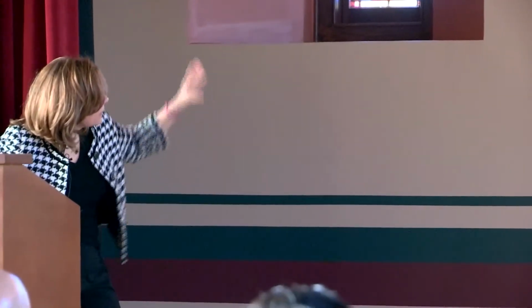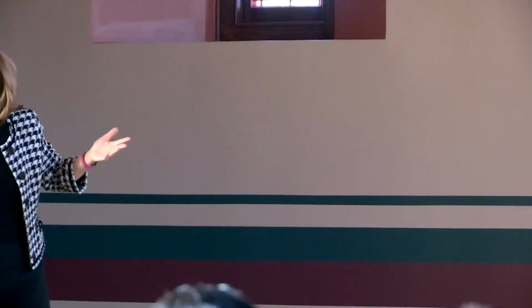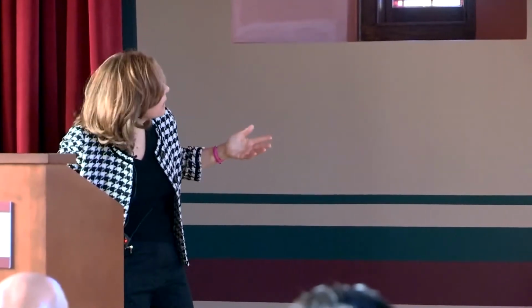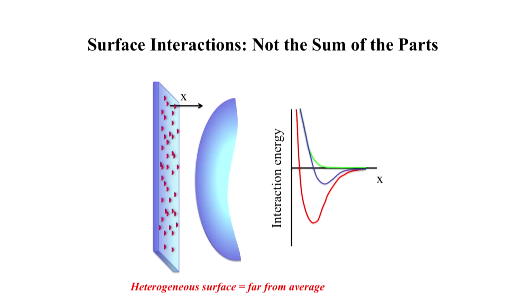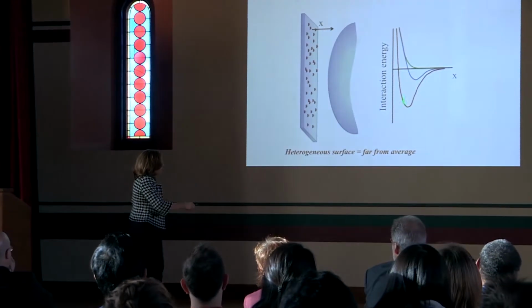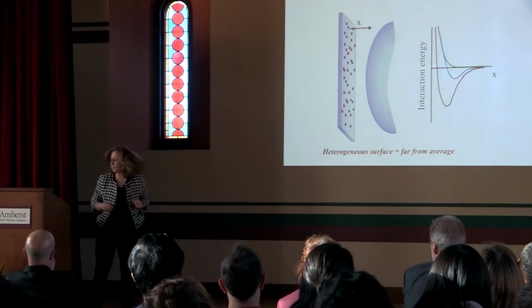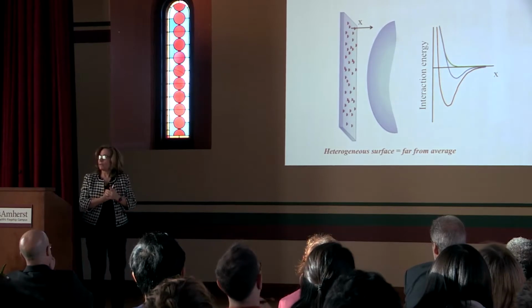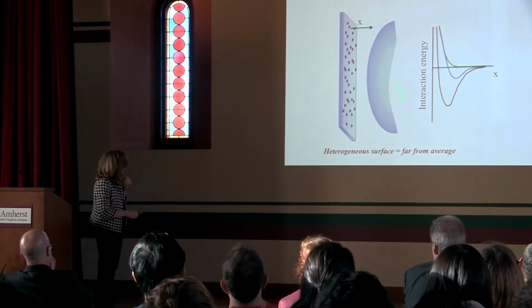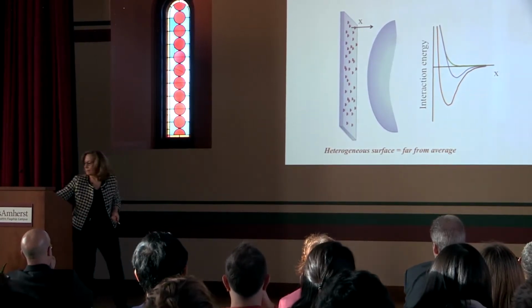Now, my lab discovered that while you can do uniform surface chemistry to make something like this happen, you get a very different result if you take the same chemistry and the same amount of surface chemistry and just put it on the surface differently, if you cluster it into tiny lumps instead of smearing it uniformly on the surface. In that case, you quite often get an interaction that's far more attractive than the situation where the interactions are smeared out uniformly. That attraction might still give you a minimum, but it means that the interfaces like to hang out more often closer together than further apart. And we've taken advantage of this unusual finding to create some new ideas about technology.